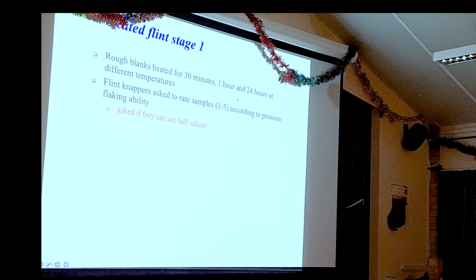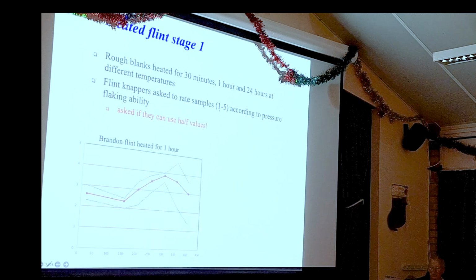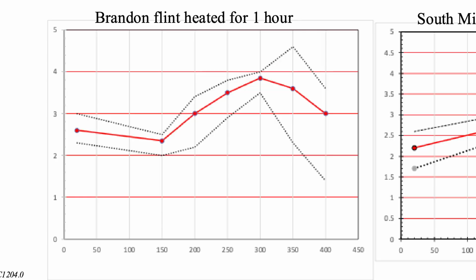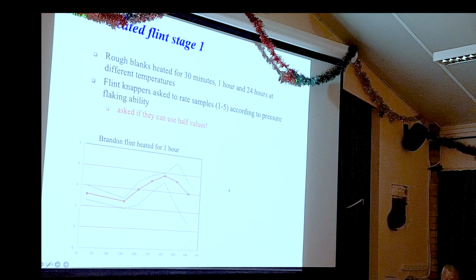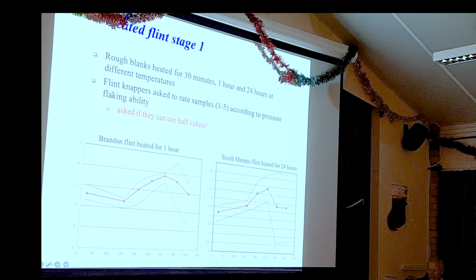So we heated samples up for between 30 minutes and 24 hours and looked at the increase in quality of the flint, which on the left is a function of different temperatures. This is a sample of the Brandon flint, this material here, which was heated for just 1 hour at temperatures up to 350 or so. This is a flint from South Mimms in Hertfordshire that was heated for 24 hours.